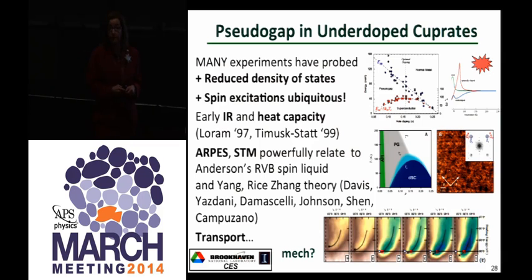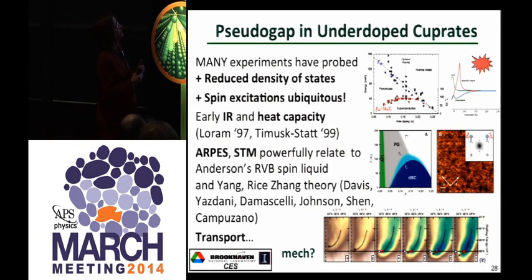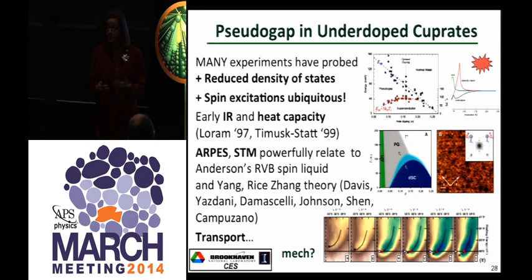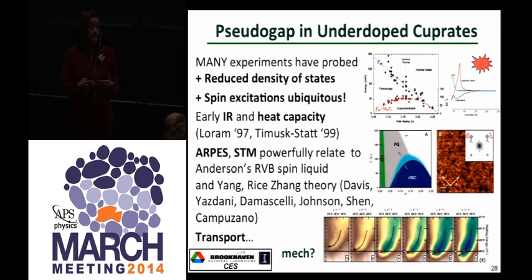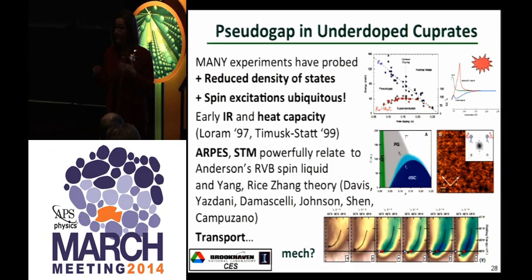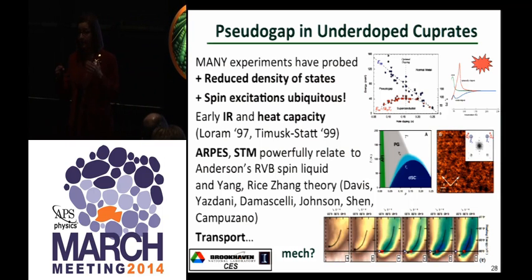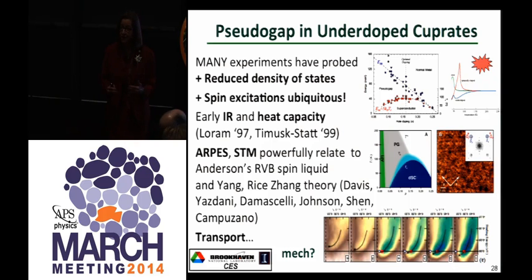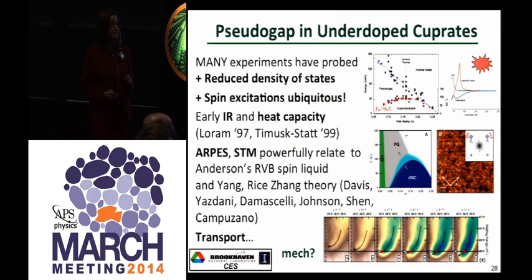The pseudogap in the underdoped cuprates has huge numbers of papers. There are many experiments that have found that, in fact, there is a pseudogap. It goes back to the optics with Tom Timusk and Stat, that there is a lower density of states and there are spin excitations. And one of the things that has been going on over and over again is that the pseudogap, the spin excitations, all this electron matter, I'm going to repeat this at the end of my talk, they seem to really wreck superconductivity. There's a competition between these ordered phases and superconductivity, but you don't get unconventional superconductivity unless you have those phases. So there's an interesting playoff there.